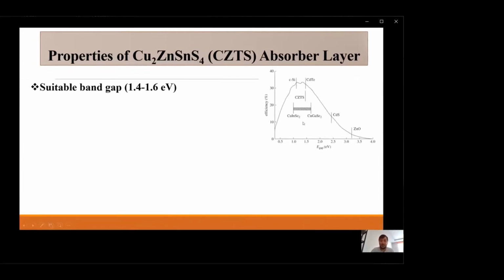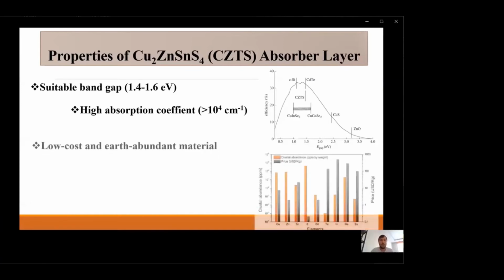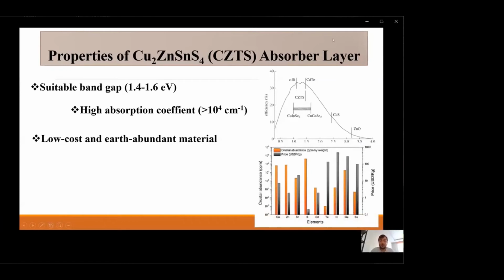As you can see in this figure, the 1.4 is around here, and the theoretical limit is about 30%. But for this kind of solar cells, the reported conversion efficiency is around 12.6. So there are so many things to do to increase the reported conversion efficiency. It has a high absorption coefficient. It means that you can absorb most of the light in a very thin layer. It has a low cost.